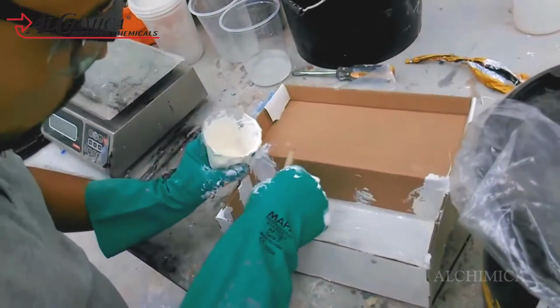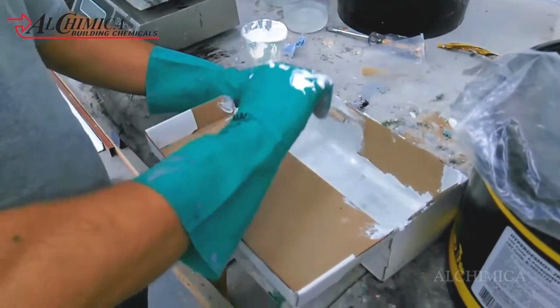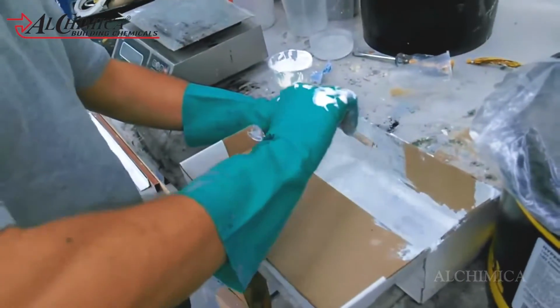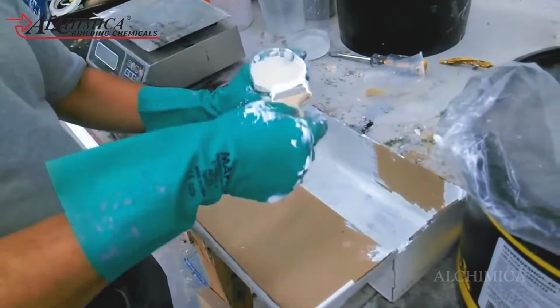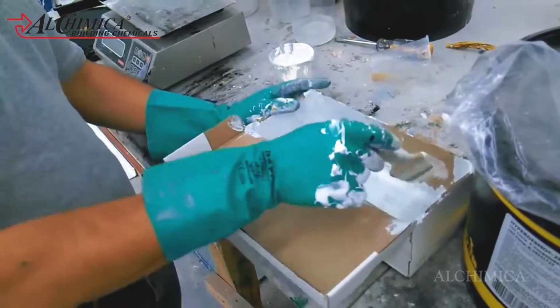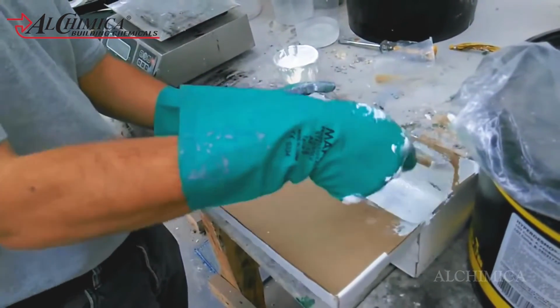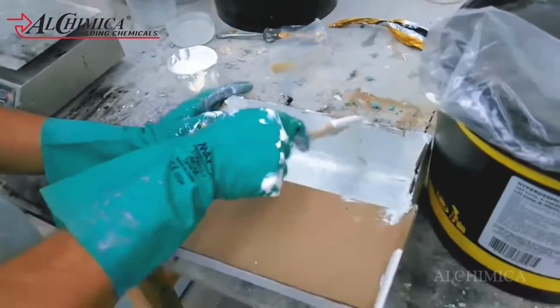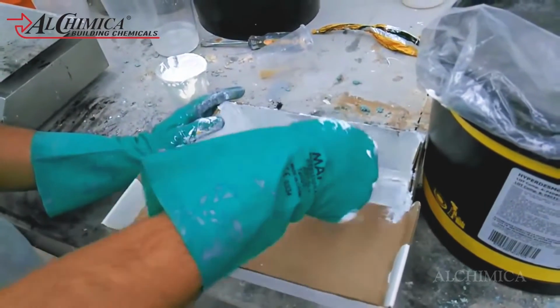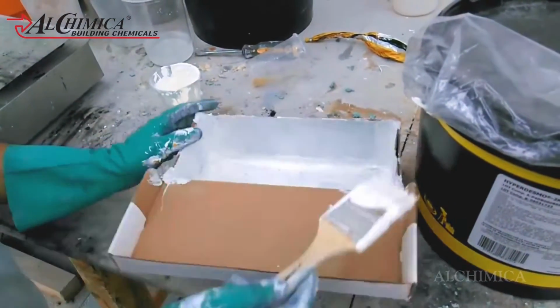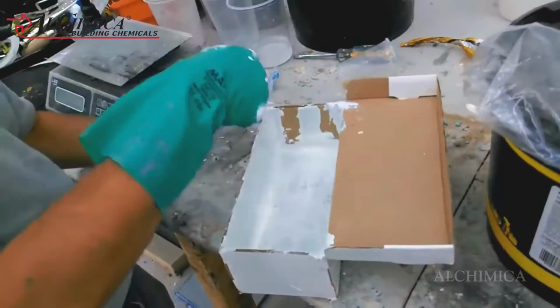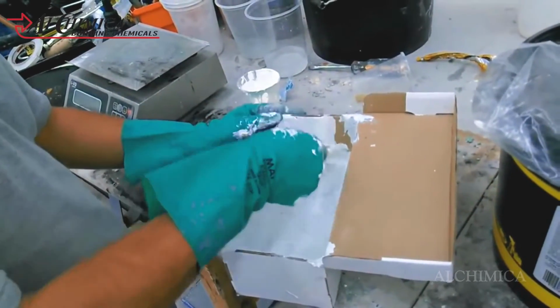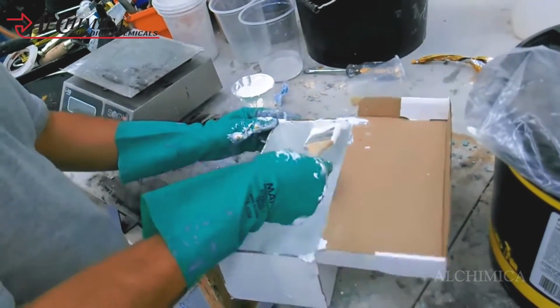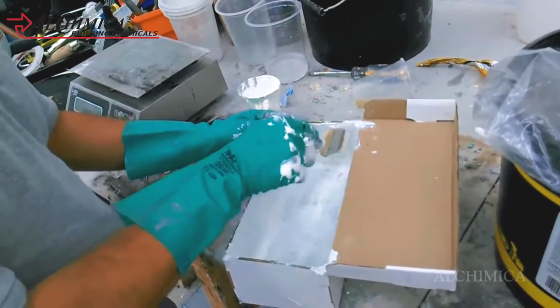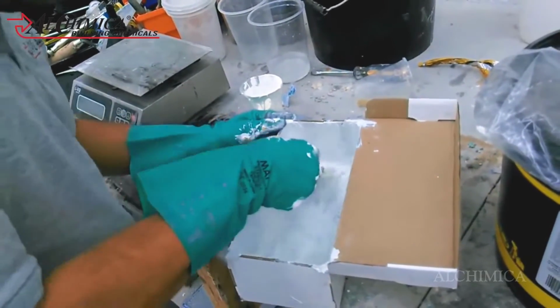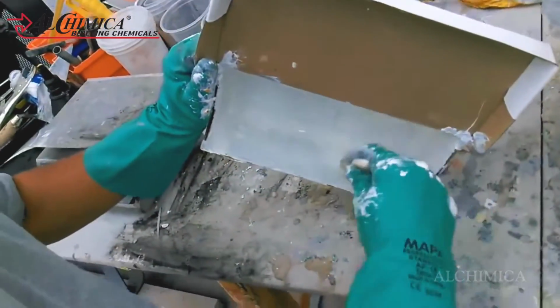For all underground water tanks, the external surface of the tanks is first waterproofed before starting the internal coating. This is to ensure no migration of water or moisture from backfilled earth into the tank. If it is not treated outside, you may observe delamination of the 2K coating or bubbles formed on the inner coat.